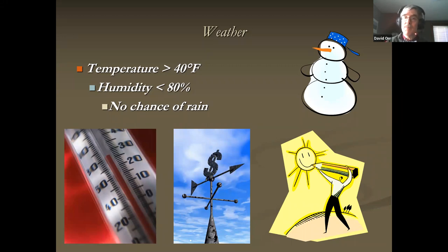Wait till the temperature is above 40, both the air temperature and the pavement. Make sure the humidity isn't too high and absolutely no chance of rain. If you've got any rain whatsoever, you're going to have an issue. So you don't want any moisture in there. It's the one thing, don't take a chance with rain, okay?